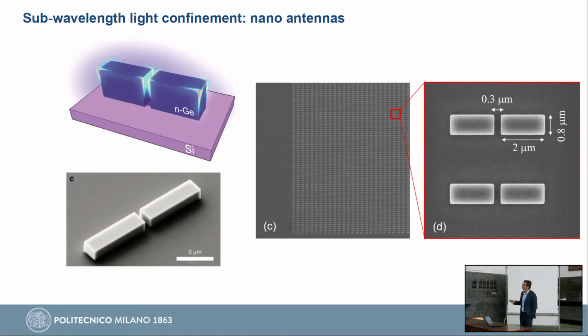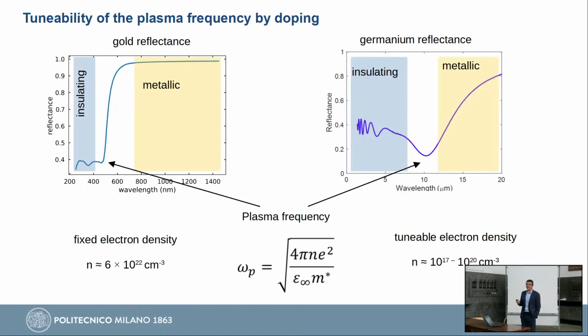Actually, for this antenna to operate, shape is important, but also the electronic properties of the materials are important. So it's actually important to work close to the plasma frequency of the material itself. So what is the plasma frequency? What you see here is the reflectance of gold. We can distinguish two main regions. One where we have a very high reflectance, which is essentially where gold has a metallic behavior, so it's highly reflective as we see it with our bare eye. And one where gold is transparent, and so it behaves more like an insulating material.